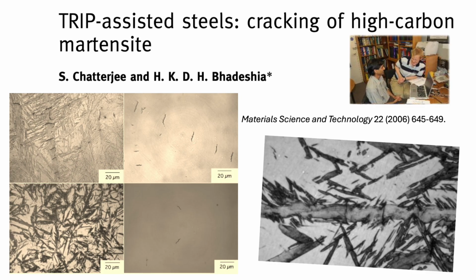And there was another point too, wasn't there, about coarse grains favoring the longest plates. Yes, that's a really important second effect. It's not just that coarse grains allow long plates. They seem to have an exaggerated tendency to form the absolute longest possible plates within that grain. So bigger grains don't just mean bigger average plates, but also a higher chance of getting those really long, problematic ones. Exactly, which makes controlling that initial austenite grain size even more critical. You really want to keep it fine to suppress those longest, most crack-prone plates.